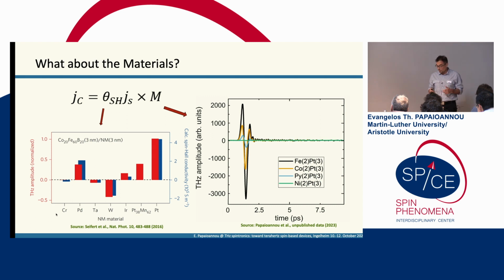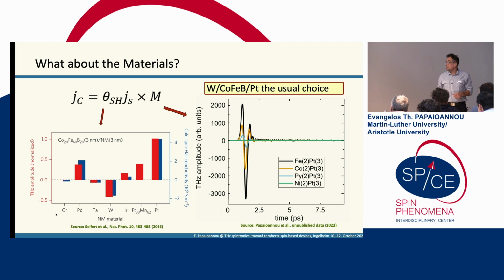Okay, so what I can show you today is different. Usually, this is the case that most people in the literature use: the tungsten, cobalt iron boron, platinum tri-layer. The tri-layers, because of these opposite spin Hall angles, show the highest signals.